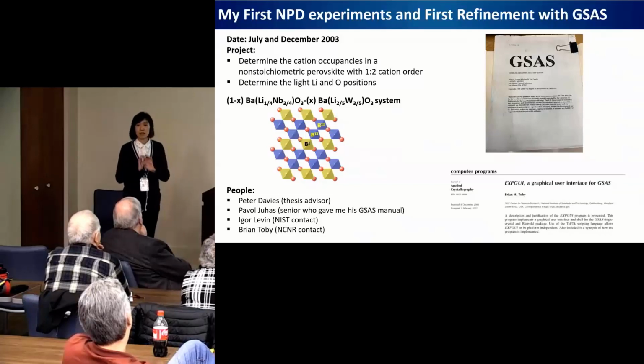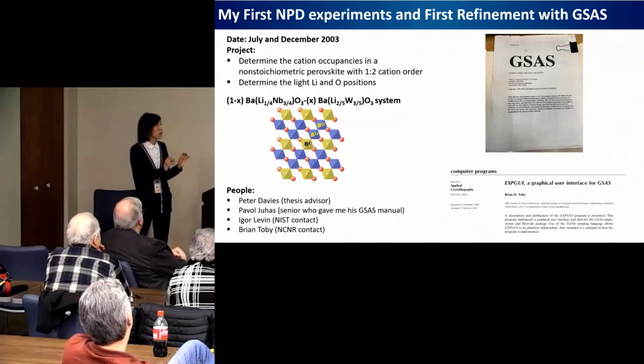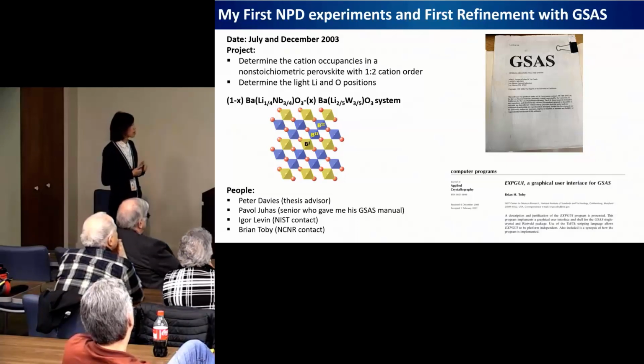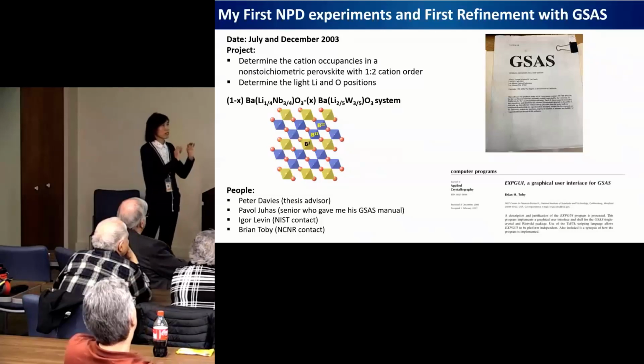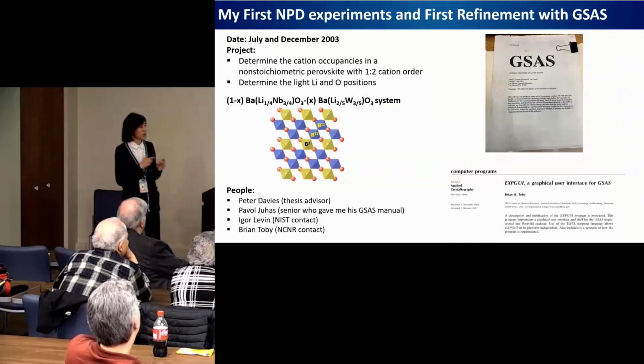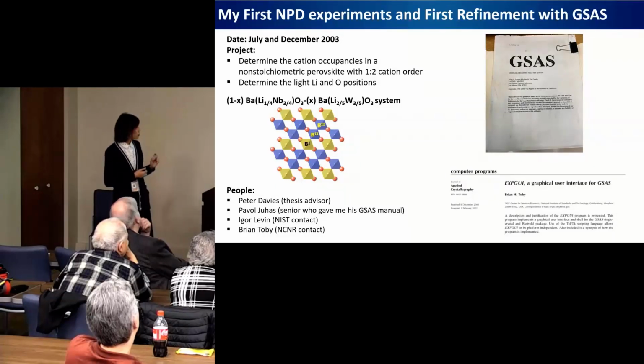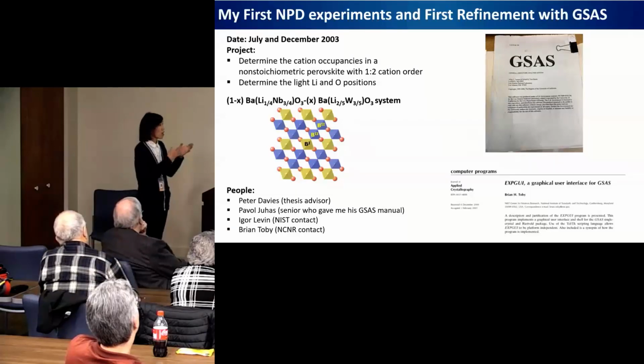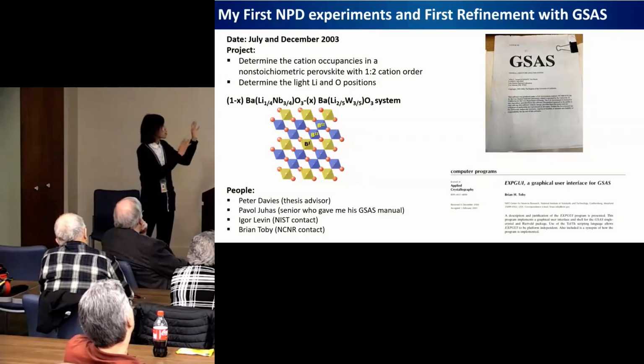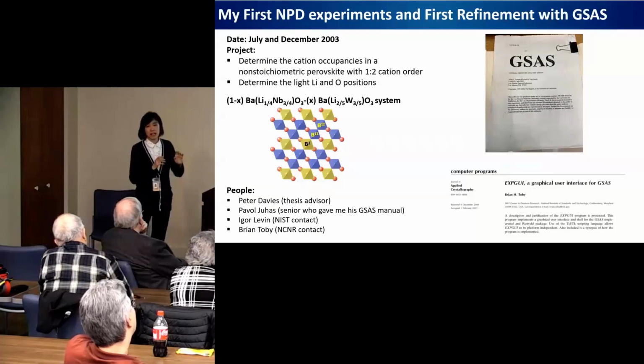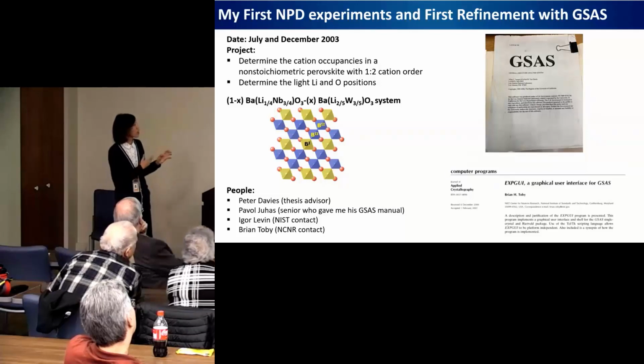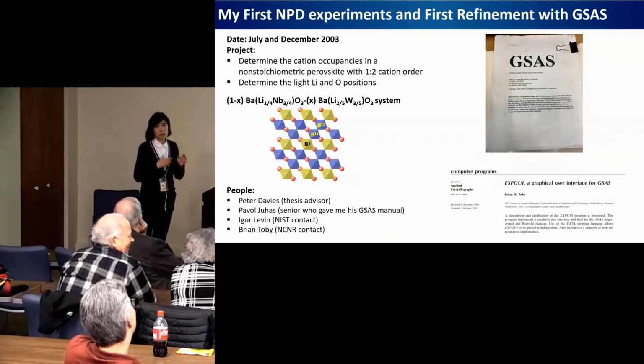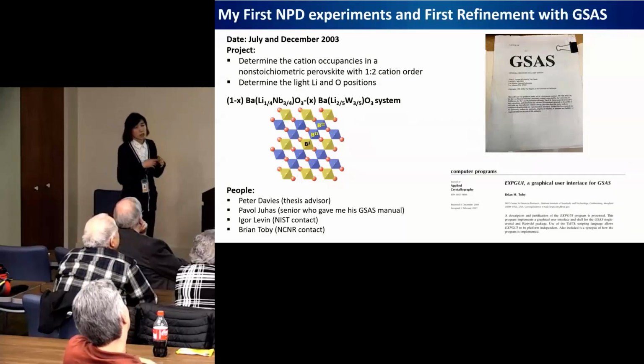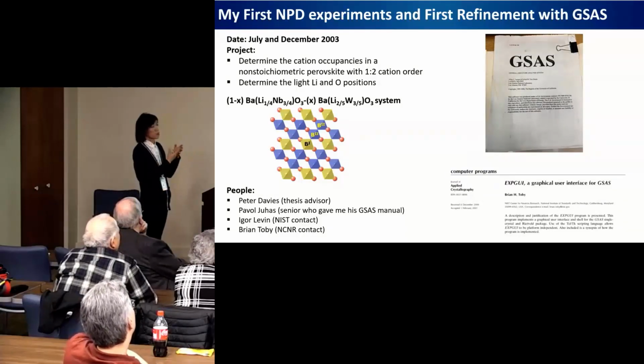Then I discovered the existence of some cubic perovskite in some solid solution range within this binary system. This means that in the ABO3 single perovskite structure, the one type of B cation will split into two different sites, and then they alternate in different orders. Because I have three elements for the B site in this system, I wanted to understand how they distribute on the two sites, and also determine the location of lithium and oxygen. For lithium, I also wanted to determine its occupancy. And for oxygen, I wanted to see if there is any octahedral distortion upon cation ordering.